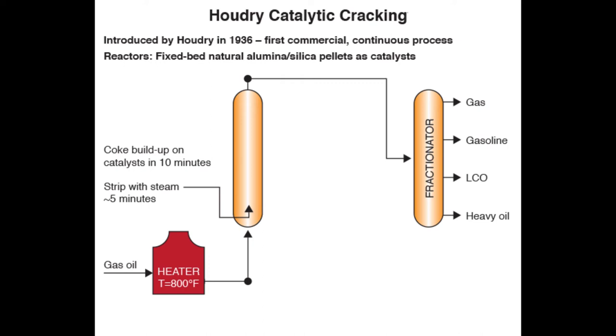Once the catalysts are deactivated within 10 minutes — all coked up — you bring in steam to strip the liquids, somewhat heavy liquids, that are sticking onto the catalyst surfaces, to remove them into the fractionator. Some of this will end up as heavy oil.